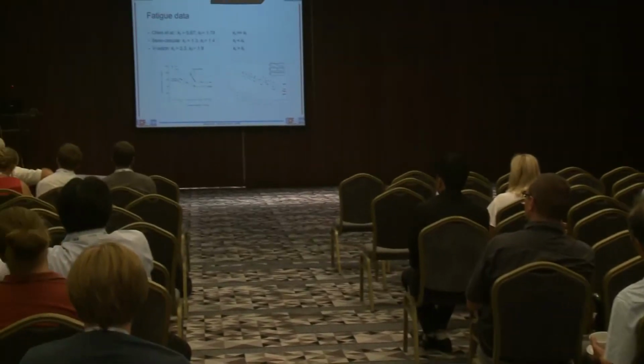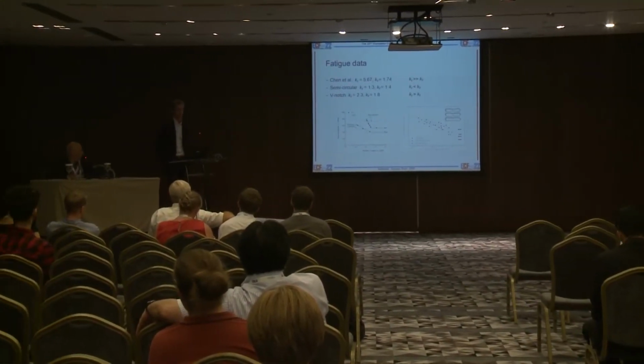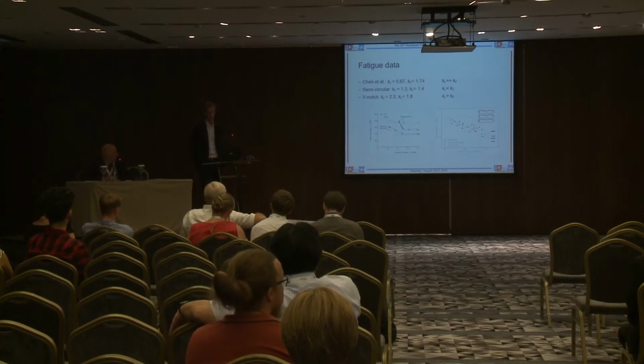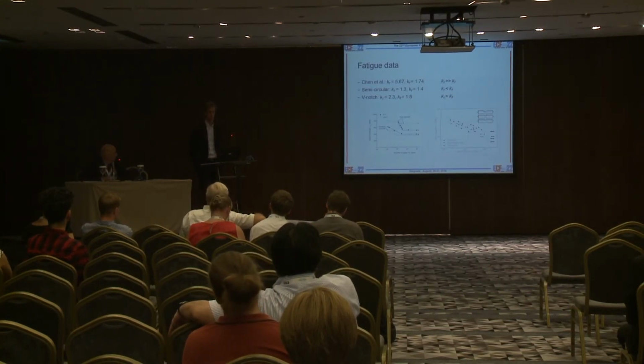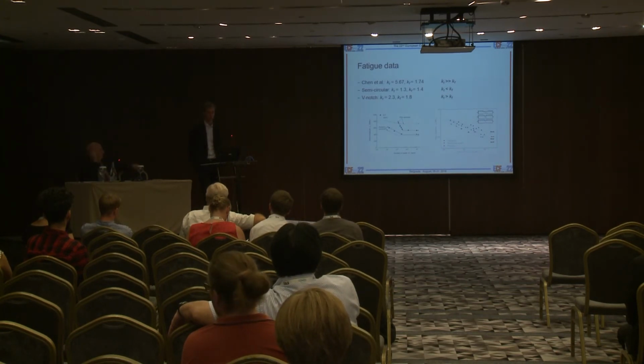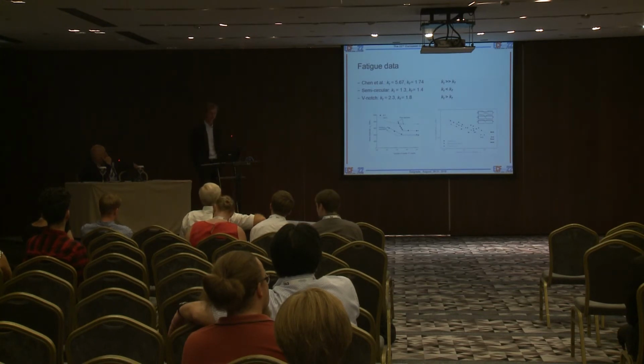You mentioned heat treatment, but that all of these tests had been done in the as-built condition. Does that imply that you're planning to use as-built components without heat treatment? In some cases, if you have a really complex geometry, like the ones I showed you, then you're not always able to heat treat because it can buckle. So of course, you wish to heat treat it, but in some cases you're not allowed, or you're not able to do it. We're starting with as-built and then going forward.